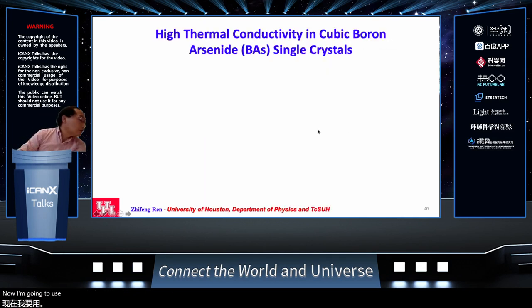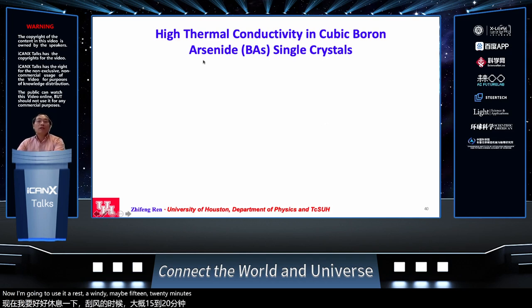Now I'm going to use the remaining 15 to 20 minutes to talk about the high thermal conductivity in boron arsenide. As I pointed out earlier, for thermoelectric materials we pursue very low thermal conductivity. But for other applications, we do want a very high thermal conductivity, like thermal management for electronic devices. Traditionally, as we know, diamond has high thermal conductivity, but diamond is so expensive and also has many other issues. Thermal conductivity has two parts, electronic and phononic. The electronic part is very much related to electrical conductivity, which is why copper and silver have very high thermal conductivity. And diamond has very high thermal conductivity due to the lattice part.